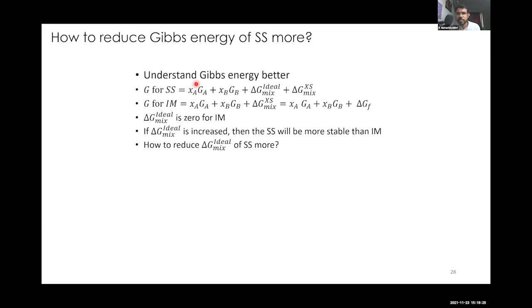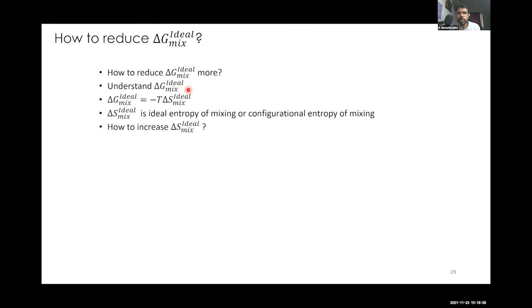This delta G mix is nothing but something called configurational entropy. This configurational entropy we should try to increase. Therefore, we can decrease the Gibbs energy for the solid solution. So here you can see T delta S mix ideal, that is the configurational entropy of mixing. If that is increased, we can stabilize the solid solution.